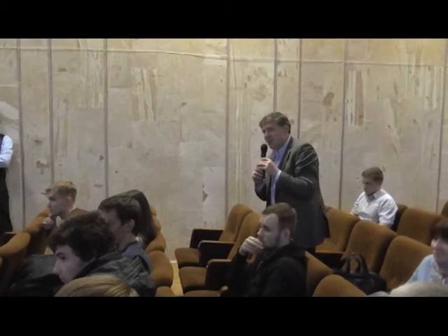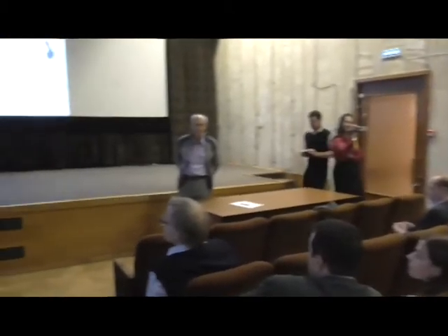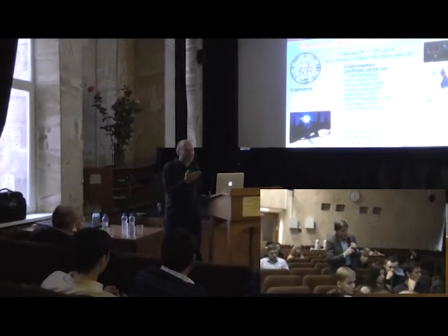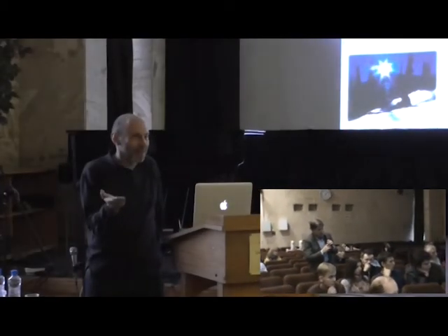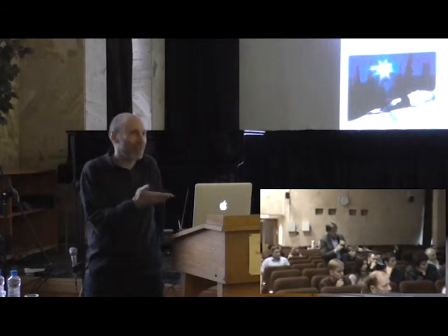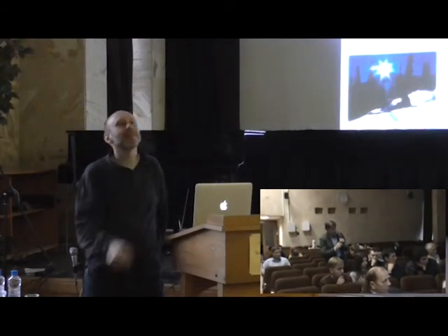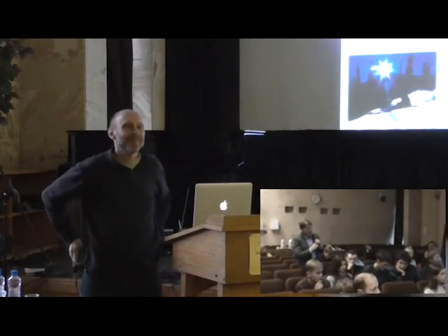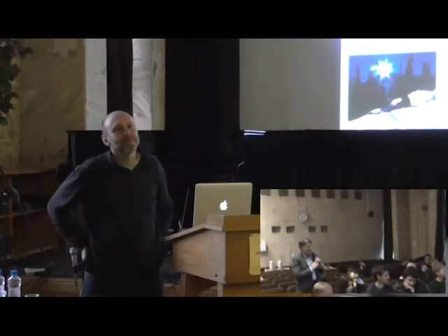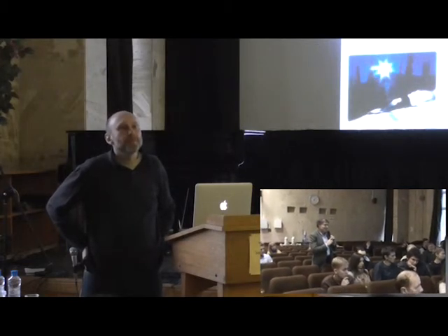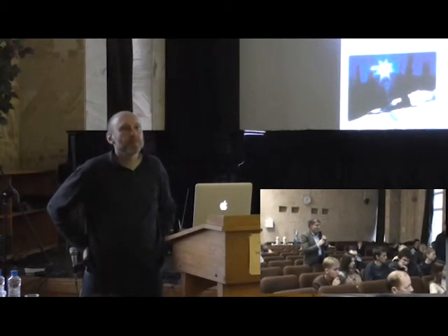The question is what you are aiming at, what you would like to calculate. If you want to calculate knock-on damage, DFT with GGA and MD should be perfectly fine. Are you sure? Because we are dealing with defects. Defects create levels in the gap, and if the gap is wrong, then the entire defect creation process may be completely wrong.